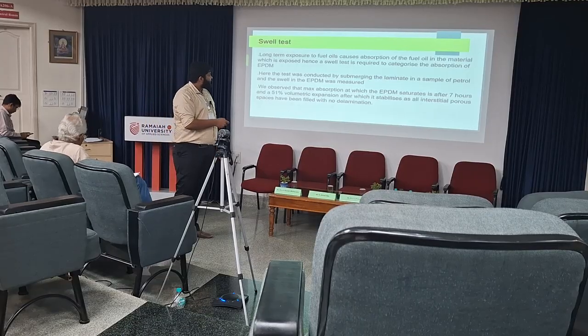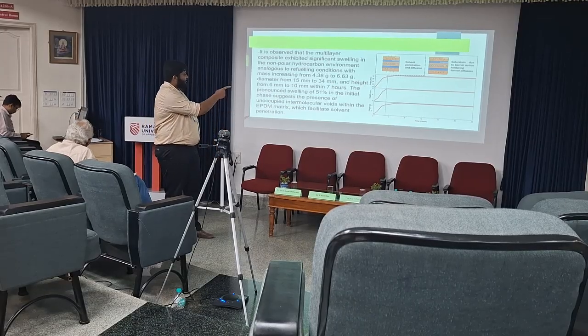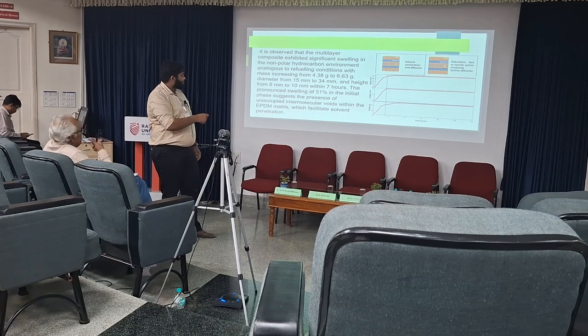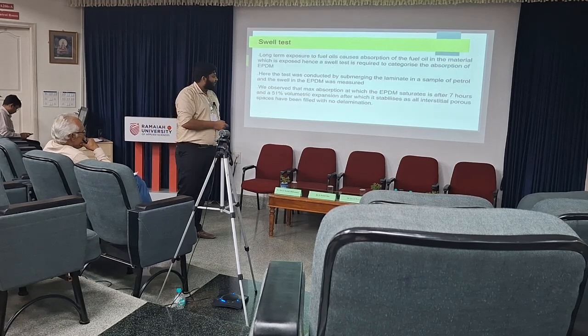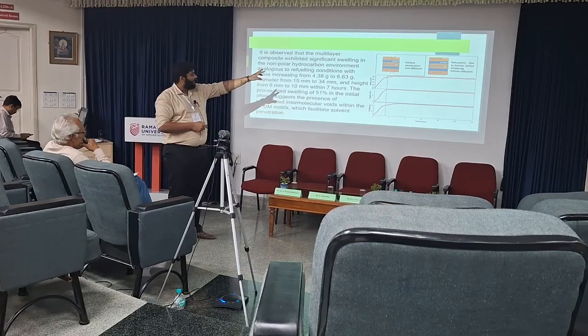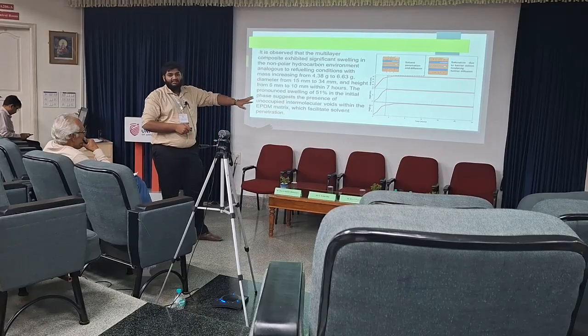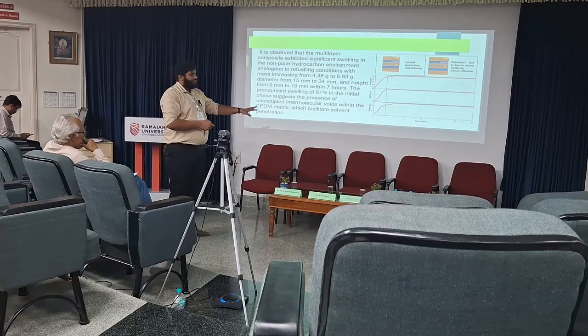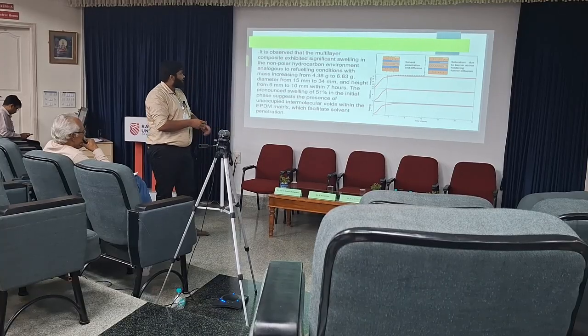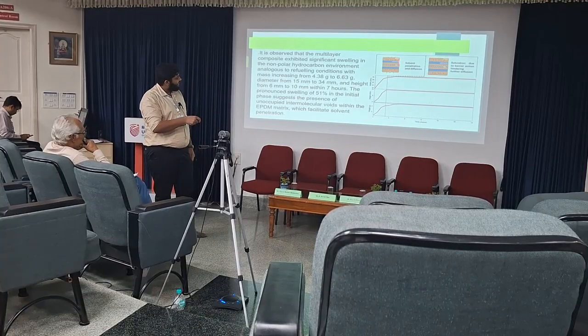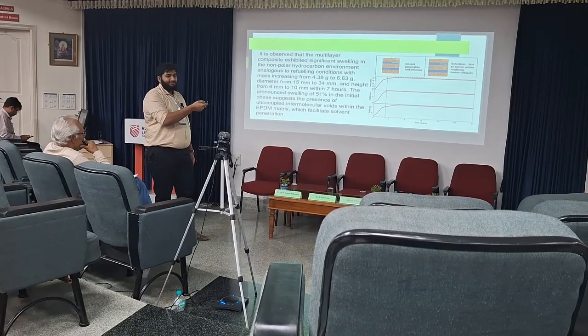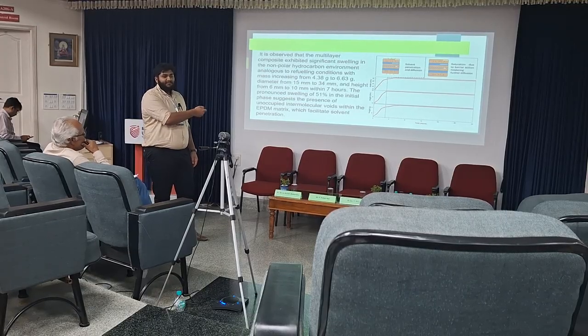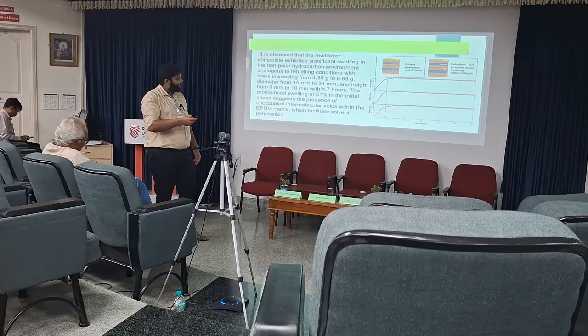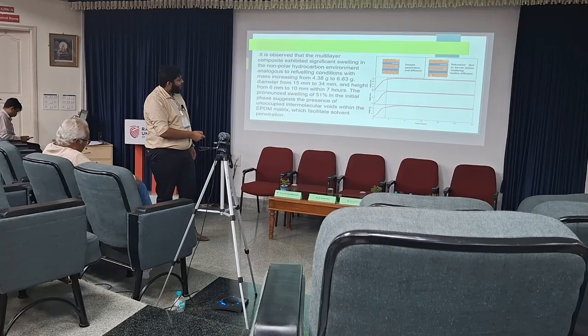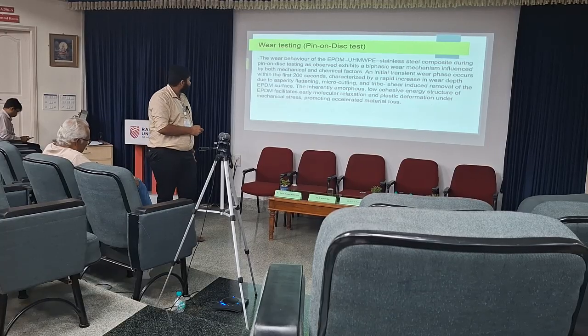So here we see a 51% volumetric expansion upon absorption, and after 7 hours the whole laminate actually saturates and doesn't take up any further fuel, because this is a mildly porous material, so any fuel oil that has seeped in has filled up all the interstitial spaces. So after 7 hours there is barrier action and any further influx is hindered.